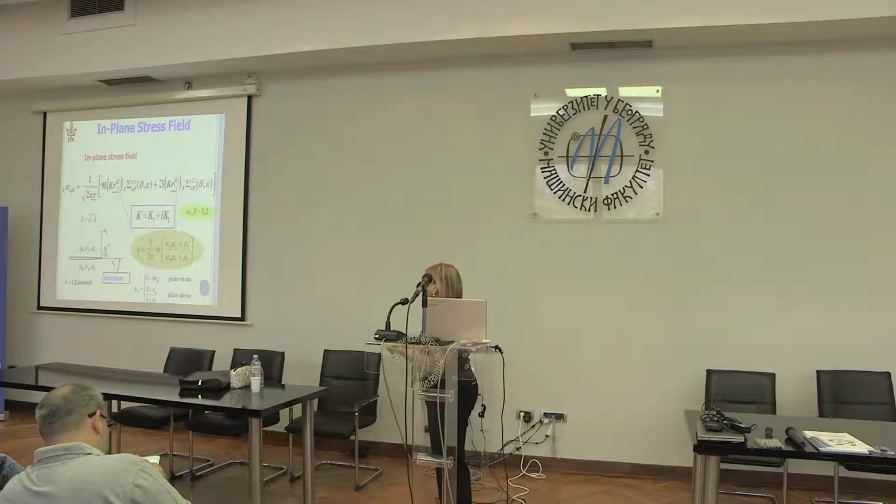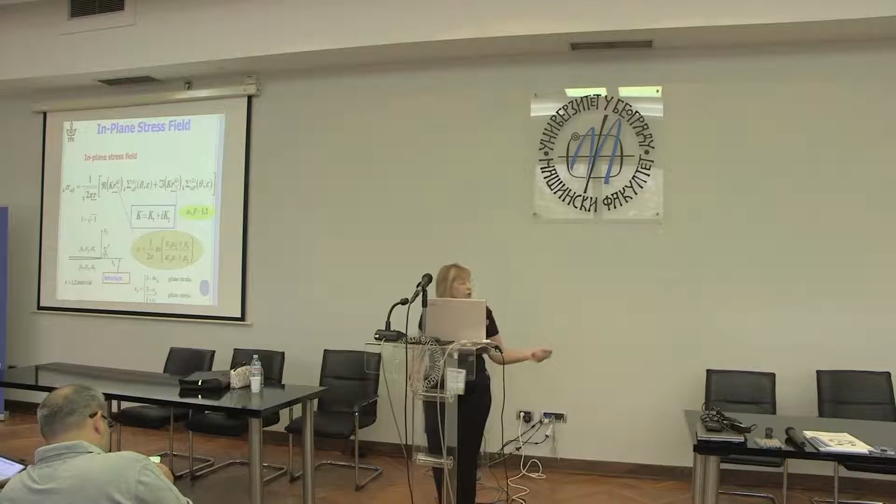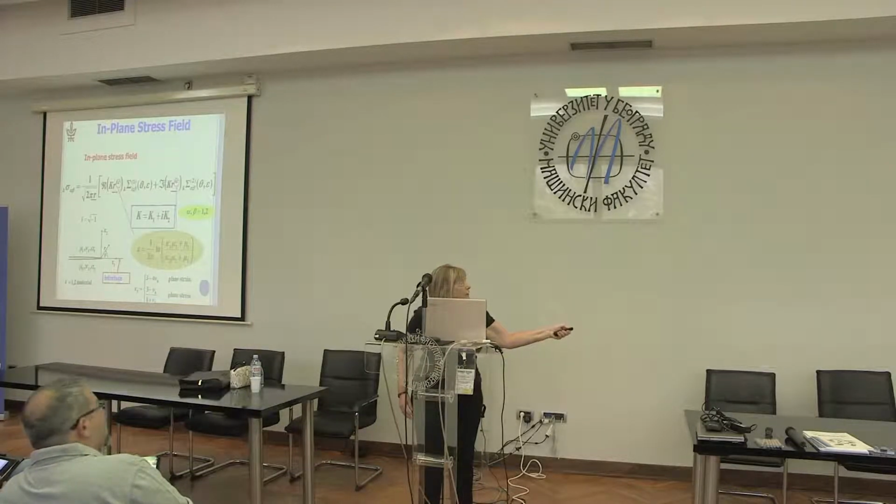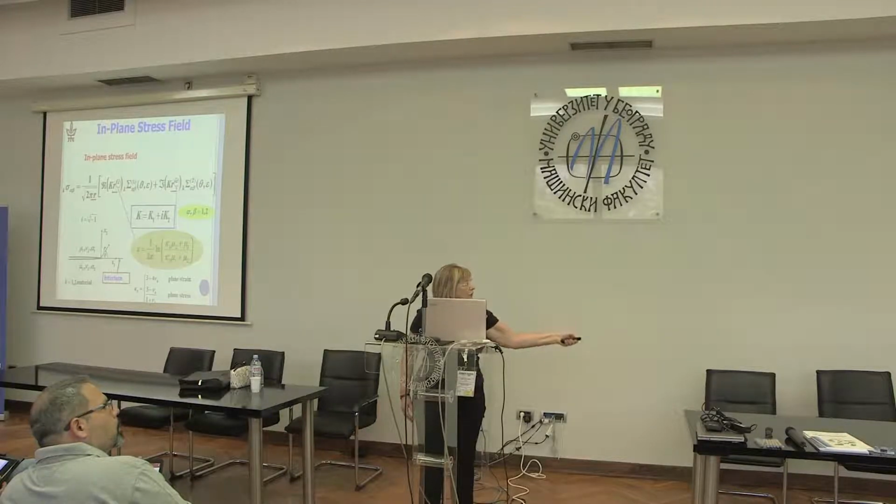So we have stresses which depend on R. We have the square root singularity that we're used to for isotropic homogeneous material, and then we have R to the i epsilon. We're looking at this expression as R goes to 0. So the stresses are not going to 0, they're going to infinity as 1 over the square root of R.